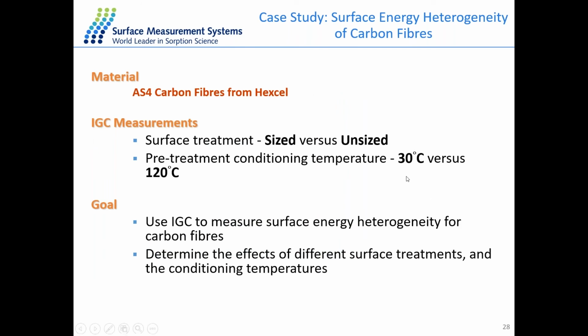So in this next case study, we're looking at the surface energy heterogeneity of carbon fibers. In this case, we're looking at sized fibers and unsized fibers. We are also looking at the pre-treatment conditions at 30 degrees and 120 degrees. So in the IGC SEA system, we can purge the material prior to any experimental analysis. And this would be the preconditioning step. So we can precondition the samples directly before we start an experiment. And in this case, we've pre-treated at 30 degrees and 120 degrees. And we just want to understand if this has a difference and if the sized and unsized carbon fibers contribute to a difference in surface energy.